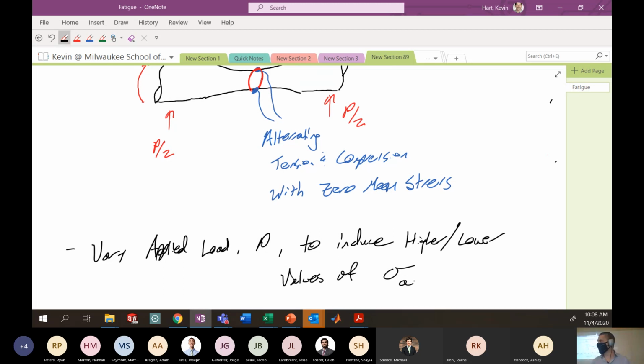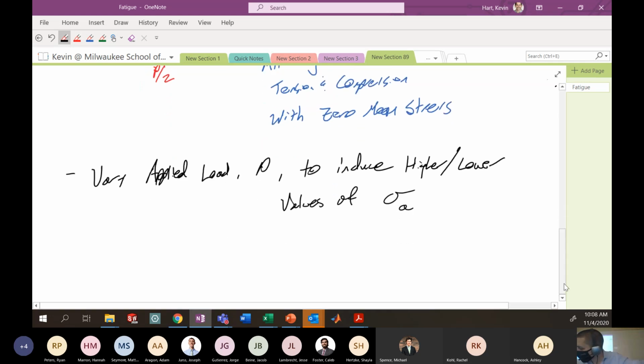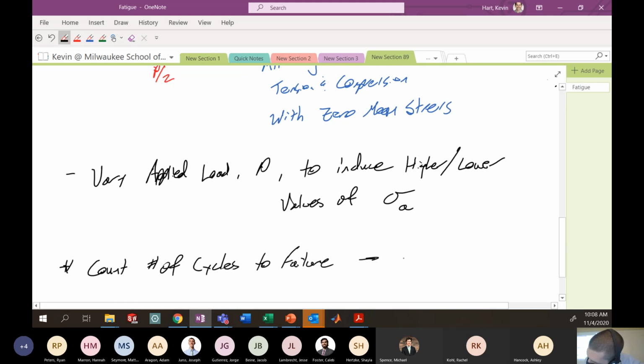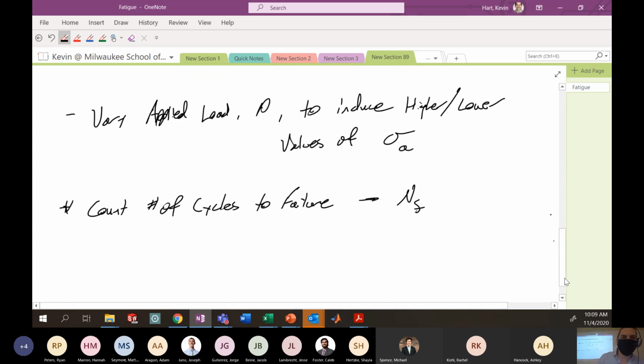We're rotating this guy while it's under 4-point bend. This cross section here is going through this fluctuating tension, compression as it spins around. And we're going to count the number of rotations that it takes before this thing fails. And we call this N_f, number of cycles to failure. The idea here then is we want to plot how many cycles to failure are required for varying levels of stress amplitude. Okay, the more aggressive your stress amplitude, the fewer cycles to failure you would expect for your fatigue. So this is the basis for what's called the endurance curve.